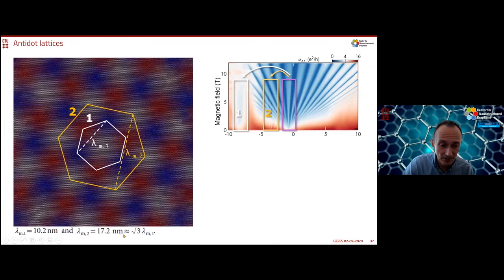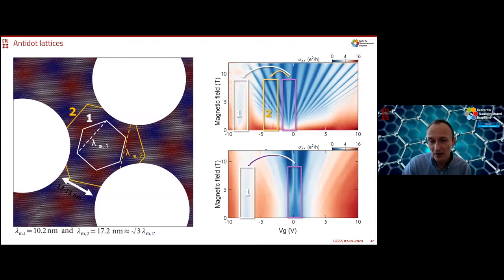So when we pattern it, the cool thing is that number two, this one, is destroyed. This is showing how big the holes are compared to this lattice here. But the small period, although the graphene is heavily, densely patterned, you still see the signature here. It survives the patterning, which means that some aspect of these moiretronics, really subtle interlayer interactions that give rise to changes in the band structure, can survive this dense bombardment and removal of carbon atoms. So the boron nitride is far more effective in protecting the graphene than we even hoped for.